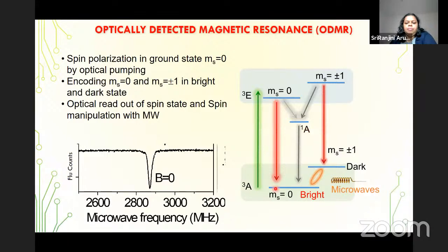When we hit it with a green laser at 532 nanometers, it goes to the triplet E state, and then from the spin state m equals 0 to m equals 0 of the ground state, it comes back emitting red light at 637 nanometers. This is 100%, and we call this a bright state. But it also transitions to another intermediate singlet state, and from the other spin states, ms equals plus or minus 1, it comes back, and some of the radiation is lost in that pathway. This is called a dark state. So we have two distinct states, one bright and one dark.